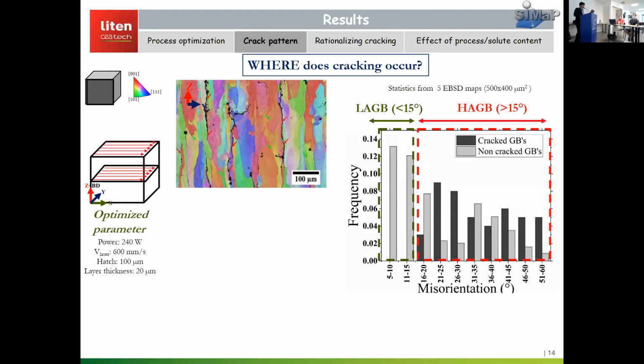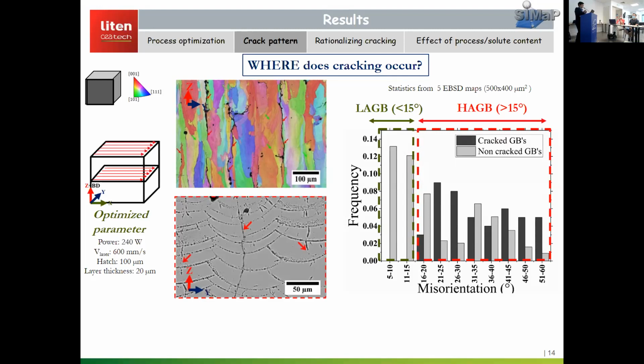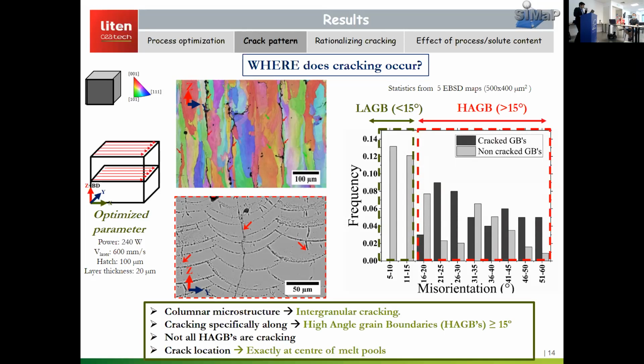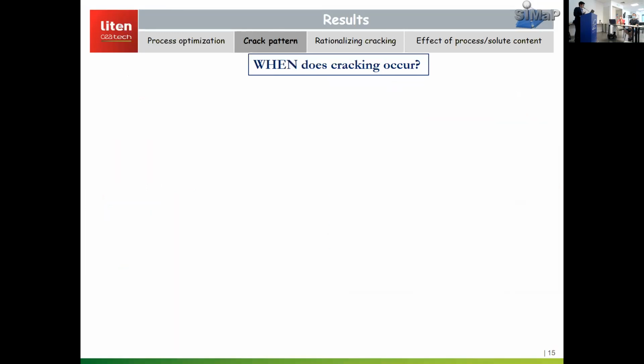To identify why these high angle grain boundaries are non-cracking, we looked at the relation of cracking with respect to the melt pools. We clearly see that cracking is along the center of the melt pool. And this explains why certain high angle grain boundaries which are located away from the melt pool, which are not localized in the center, can be non-cracking. So cracking is intergranular in nature, occurring along high angle grain boundaries and exactly at the center of melt pools.